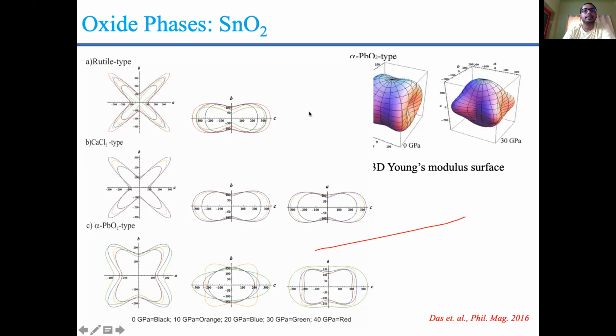And on the AB plane, the modulus increases along the diagonal, and when the pressure increases to 30 GPa, you can see the stiffness ratio goes almost double.